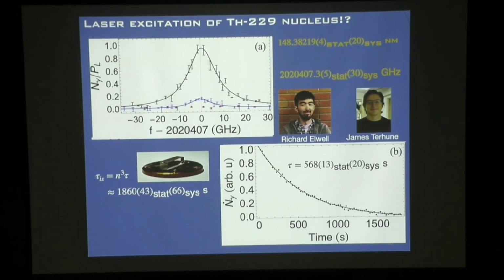I had said earlier that we would expect this thing should be a couple thousand seconds. I've sort of left out something important. In the crystal, the index of refraction is not 1, and so the photon density of states is larger by n cubed, the index of refraction. And since this is a magnetic dipole transition, the magnetic field isn't changed in the dielectric, so overall the decay rate is enhanced by n cubed.